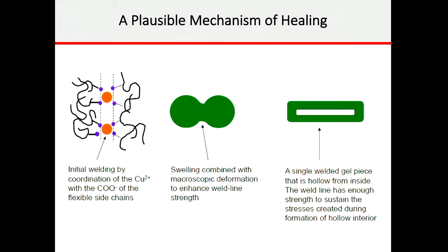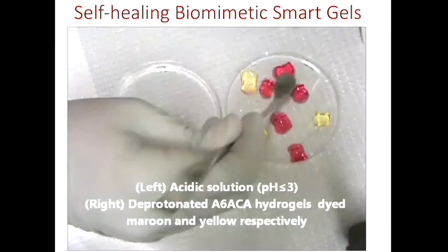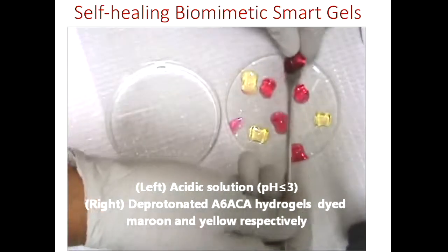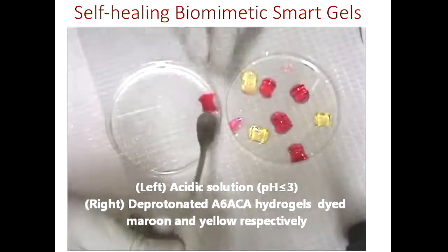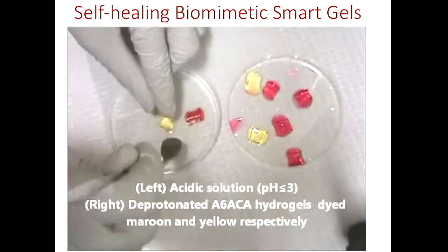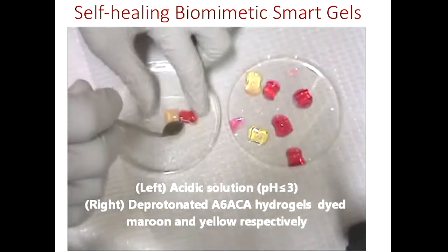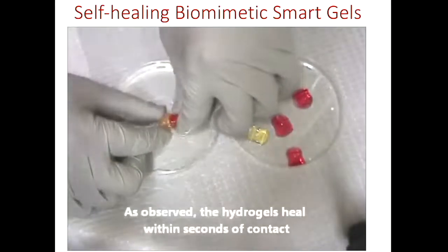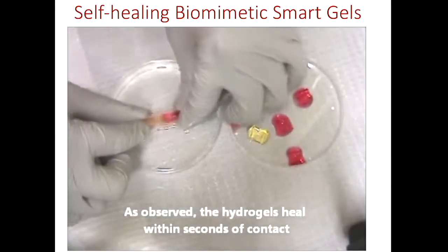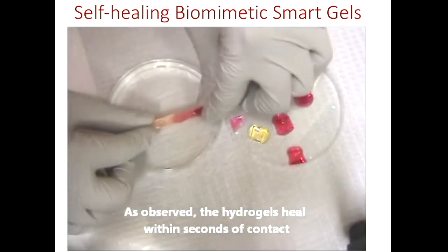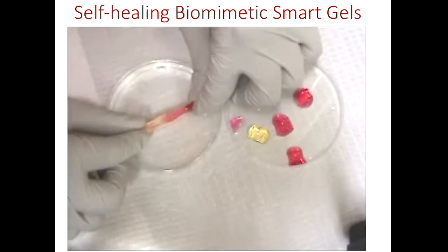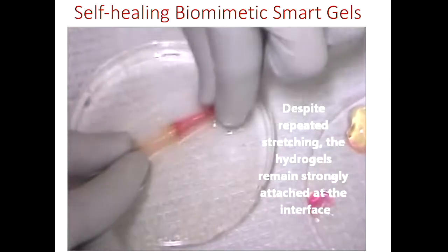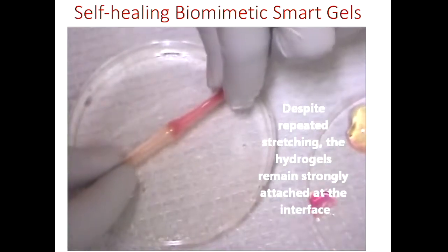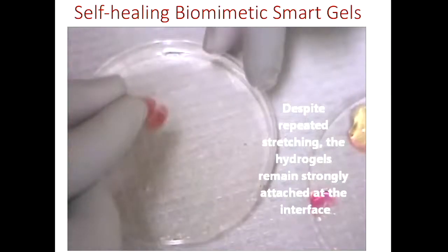And in fact, the weld line has enough strength to sustain the stresses that are created during the formation of the hollow interior, that is the pieces. We took this forward, by the way, without cupric ion, and you can see a beautiful experiment here. The deprotonated A6ACA hydrogels. You bring the two pieces together, instantly they healed. And you can see they are stretched, and yet they sort of withstand that stretching. So therefore, and this was a paper we published in Proceedings of National Academy of Science,